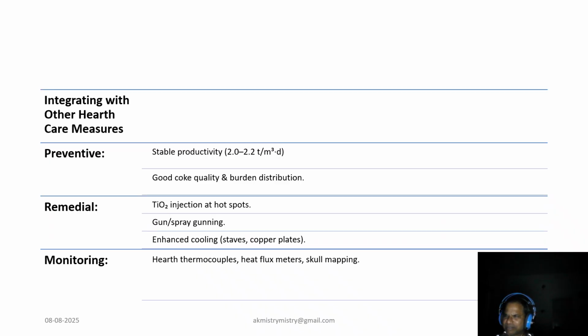Now coming to our next slide, TiO₂ is not a standalone cure. It works best when integrated with other hearth care measures, and these are also very important. Preventively, we aim for stable productivity. This is a must, and typically around 2.2 tons per cubic meter per day is important. Coke quality, burden distribution, and keeping permeability high are vital. Remedially, TiO₂ injection is combined with gunning, a spray coating, or even a stave replacement in some cases. And we must monitor: thermocouples, heat flux sensors, and occasional skull thickness mapping are all tools that tell us if the hearth is healthy or not.